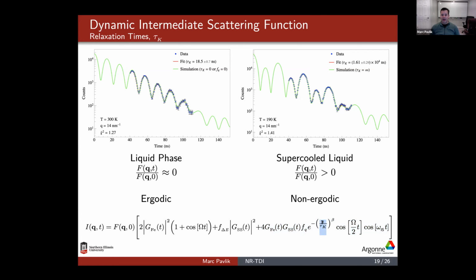eliminates that term. So I have to be careful when I get closer to room temperature, because my fitting models would try to blow up my relaxation time when this goes to 0. So I had to do some analysis that helped me get a better relaxation time. You can see a similar thing when I go to a frozen sample or a very cold temperature: my relaxation time is extremely large, which means a slow relaxation rate. The green line again is the simulation saying that the relaxation time is at infinity. Again, there's a red curve hidden behind there.